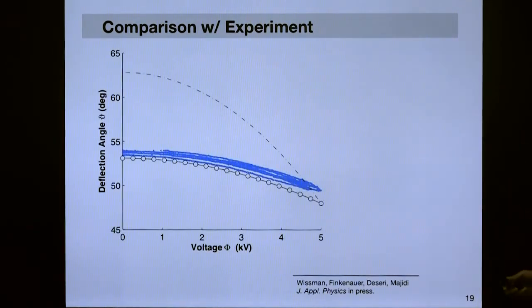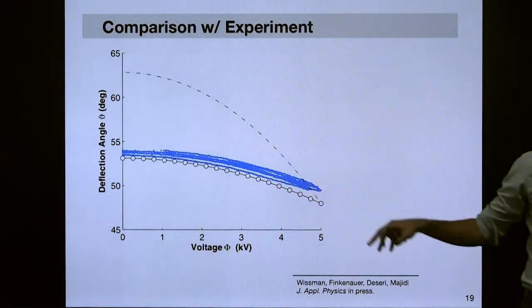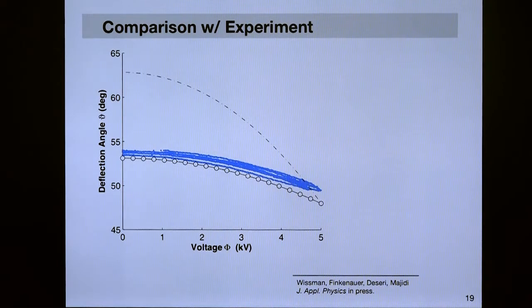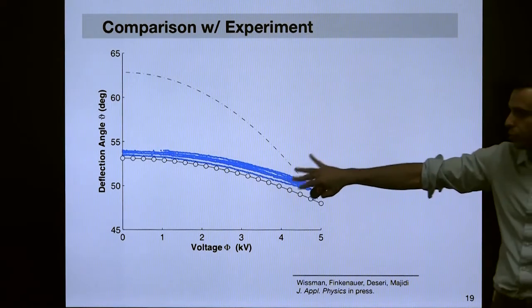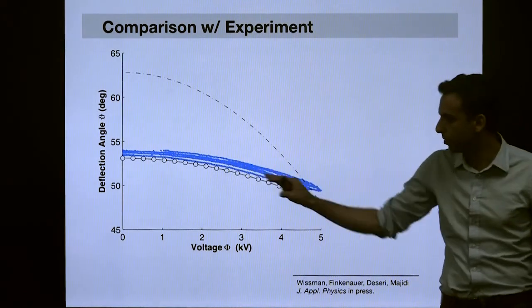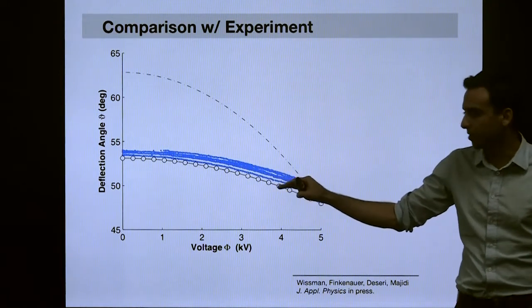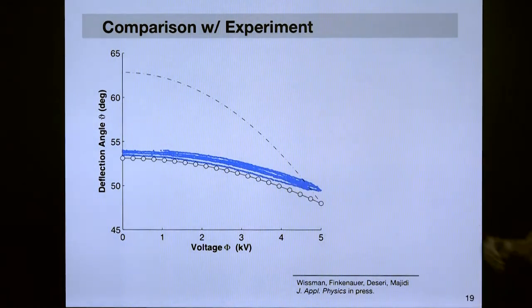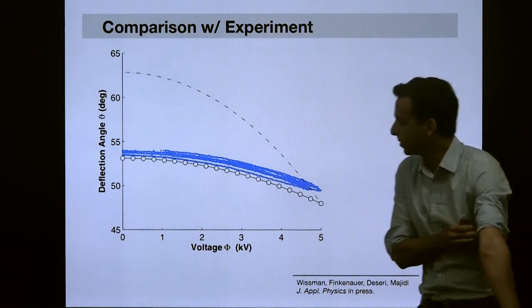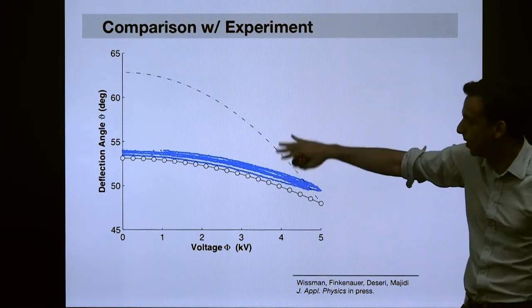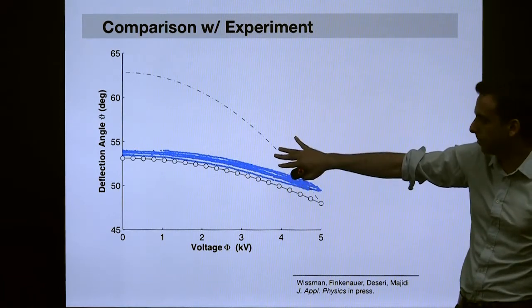When we do that, we actually get an analytic solution that is in much stronger agreement with our experimental results, and what's important is that we don't do any data fitting. This prediction is not exact, it's not perfect. Even in a shell model, there were certain simplifications we made just to make the problem more tractable.